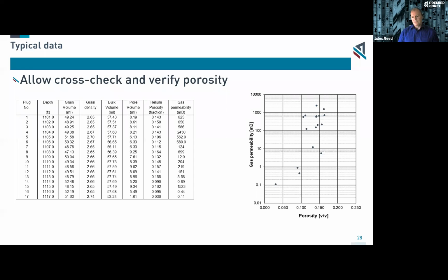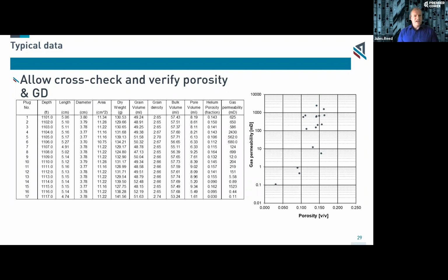We might have length and diameter data and dry weight. The dry weight allows us to check the grain density and make sure that those agree, and we can then look down the grain density data and we see one sample that is significantly different than all the others down at the bottom there at 2.74, and we can begin to ask questions about that one sample. But we also see that it's the one with the lowest porosity, so it might be expected as well. The data still potentially stands.